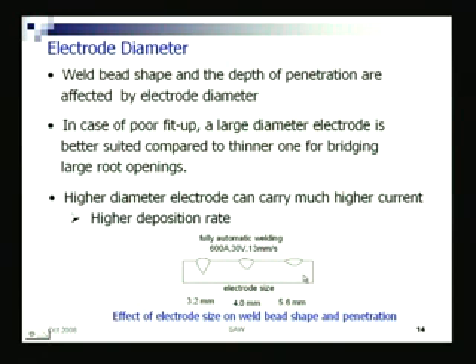Now, in this, other parameters are kept constant, because when I use a higher diameter electrode, I should also increase the current, otherwise the purpose is not served. Once the electrode diameter is high, it is capable of carrying more current. If I increase the current, I melt more metal, deposit more metal per unit time, and thereby increase the welding speed and my productivity.